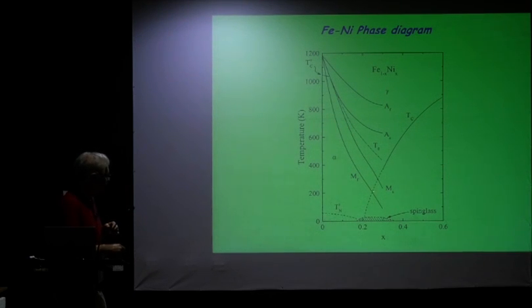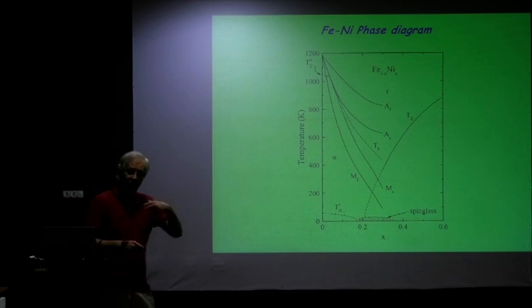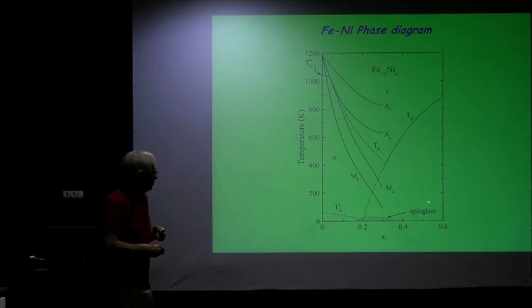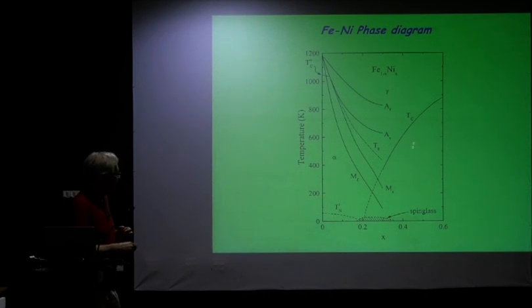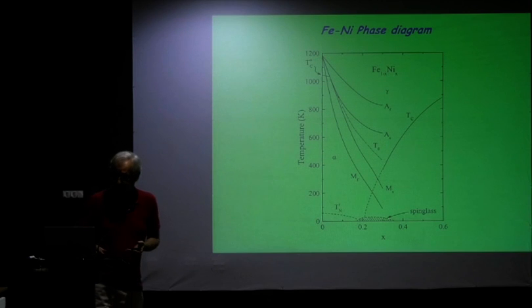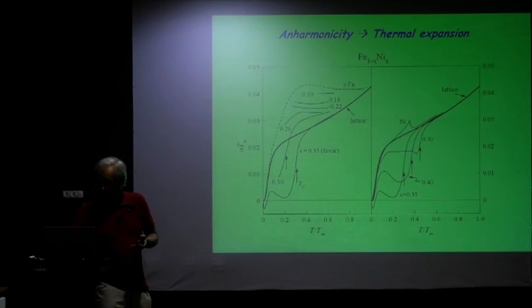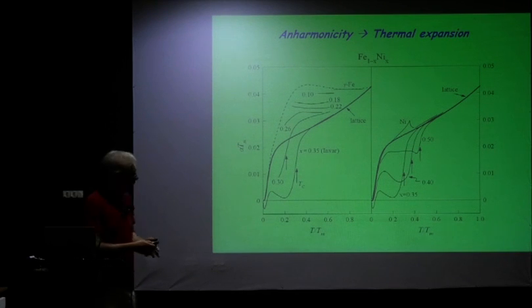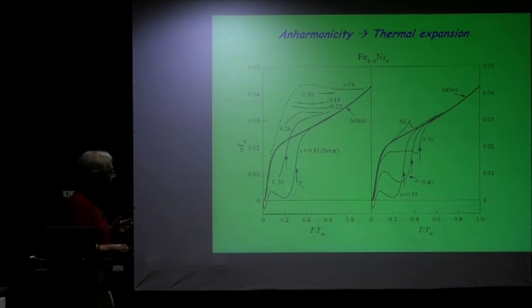These dotted lines are expected. This has to come down one way or another. This is also going down. It's not measurable. But you see, you have a region here where these meet. You have competing magnetic interactions. And at very low temperatures here, in some of these, you can see that you have a frustrated state because of the competing interactions over here, with the antiferromagnet and the ferromagnet. So this we come back to again, and we want to know now what is happening to this.